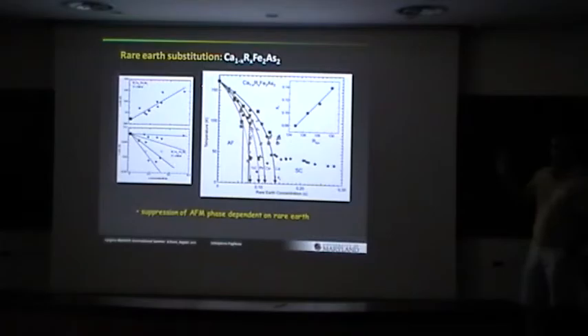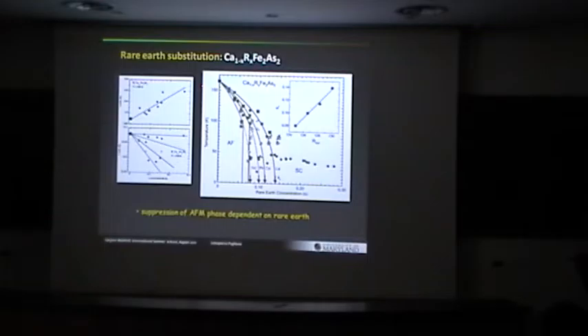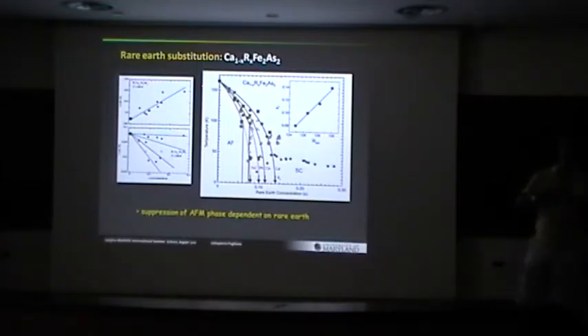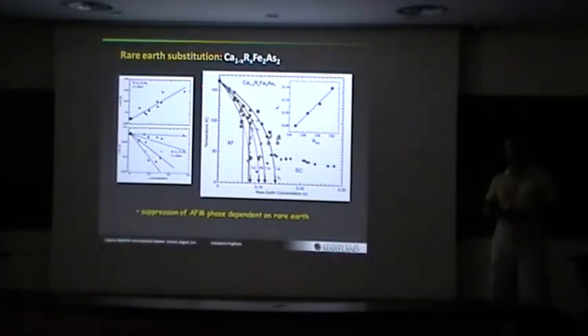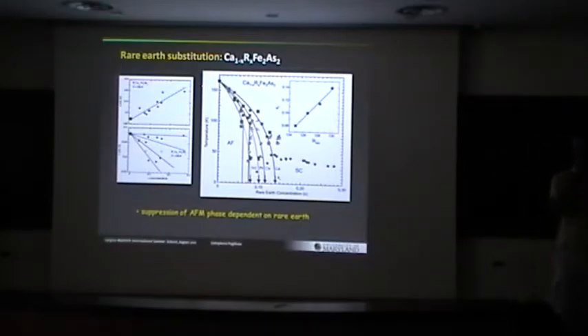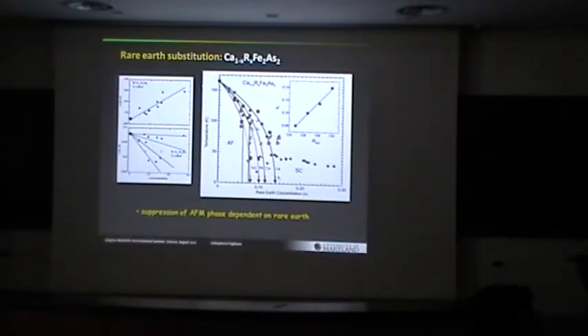But that's very strange. Once we get the chemistry under control of that system, we know exactly what's happening with this ordering and all this stuff. Those are details, I think, that are affecting the interpretation. Regarding the gap structure and so on, I try to emphasize that the gap symmetry seems to be consistent, as far as the data that we have tells us. The structure varies, and that's probably kind of detailed, as you can explain better than I will. So I think these are the key things. Anyone else want to add to that?